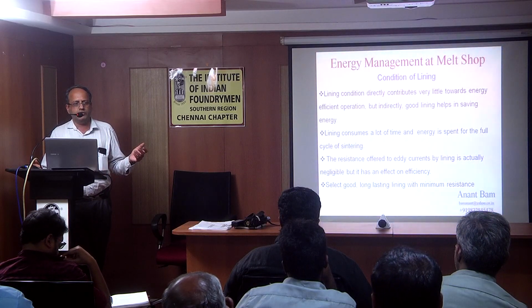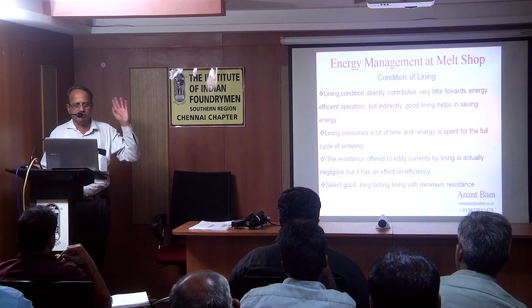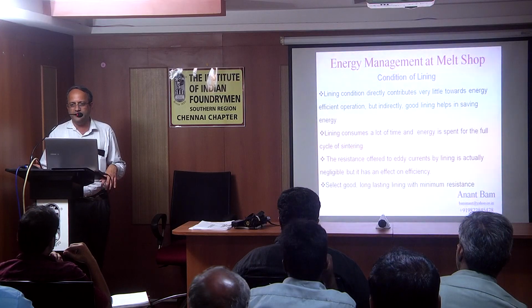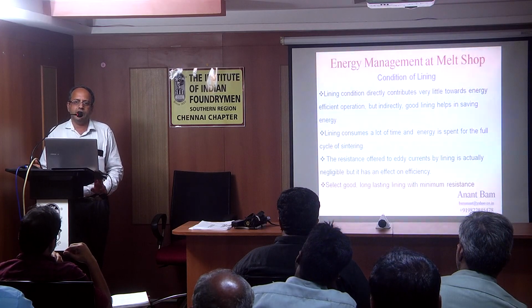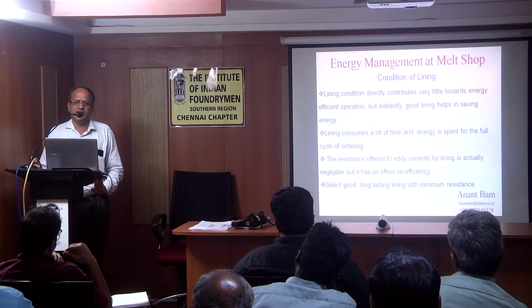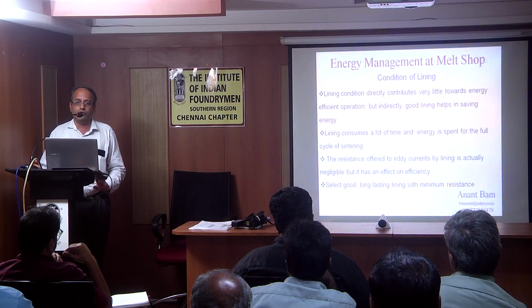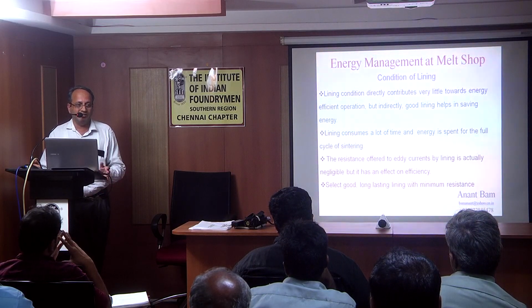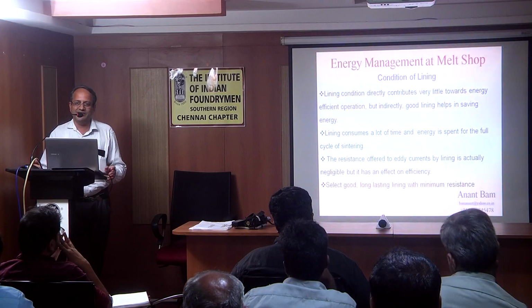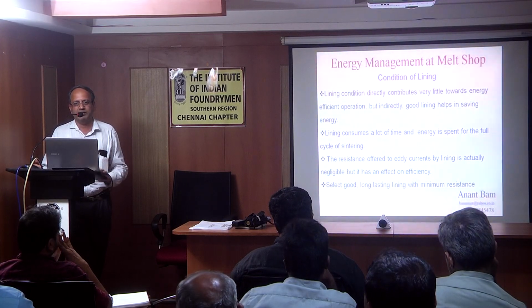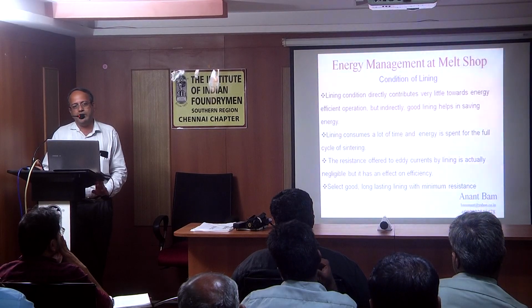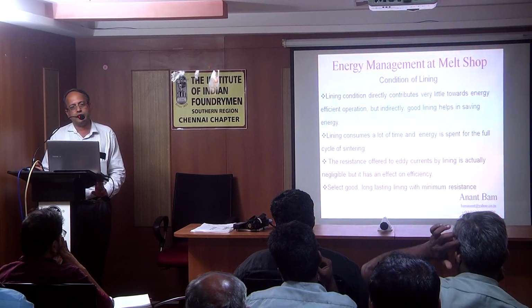There are a few foundries who do dirty work, not in Chennai, but somewhere in Rajkot, whose lining doesn't last even 100 heats, 90, 95 is that too. After 40 heats, they start patching, and at 90 or 95 heats, they break the lining. But there are some good foundries wherein the lining lasts for 1000 heats.